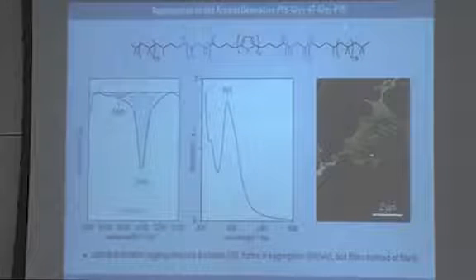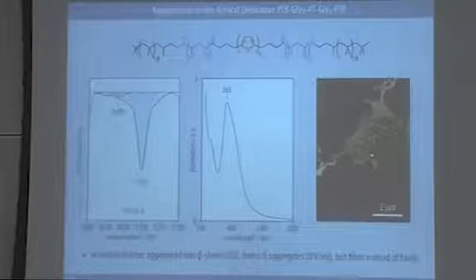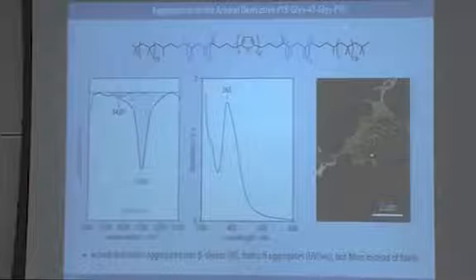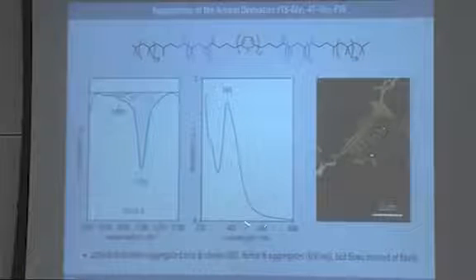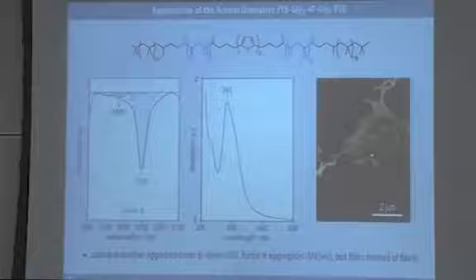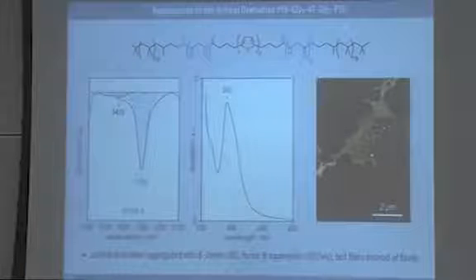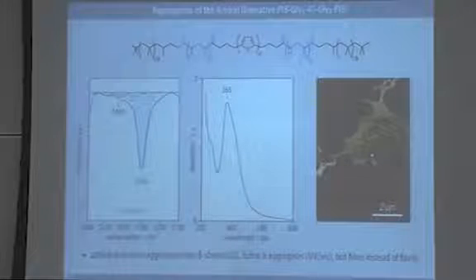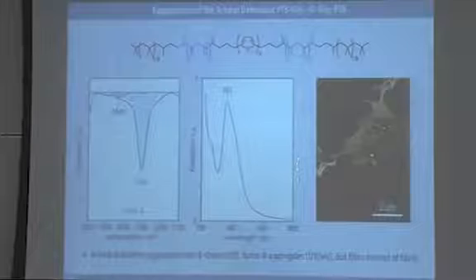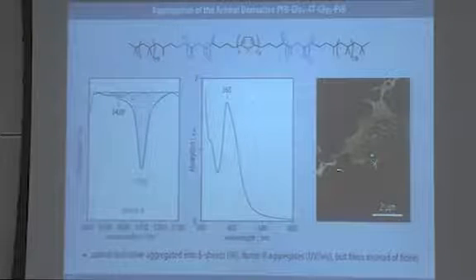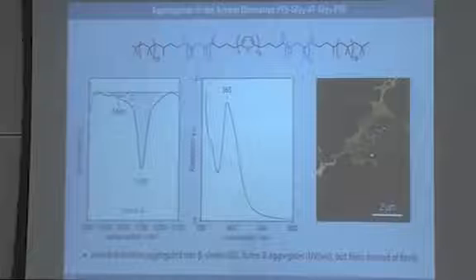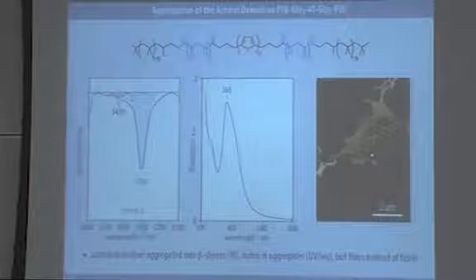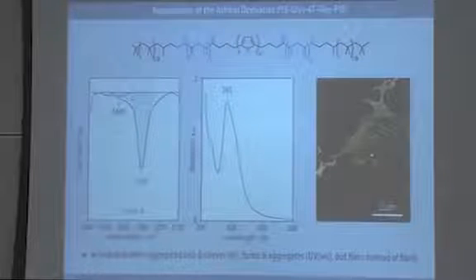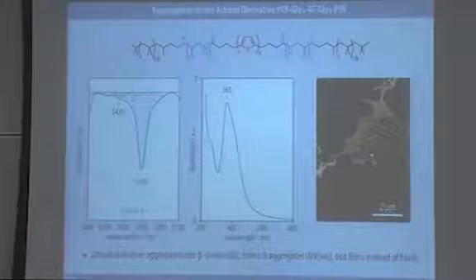The UV-Vis absorption spectrum shows a maximum at virtually the same position. So we seem to have H aggregates in this case as well, but notice the absence of any structure in this case. However, in the absence of chirality, the molecule of course doesn't make fibrils. It makes more like monolayer films. The height of these films corresponds to the diameter of the fibrils we typically observe, but we have lateral aggregation into these film-like structures. Nicely enough, we see kind of a sergeant and soldier effect.